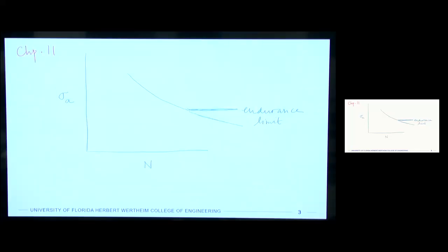And when we started the class, one thing we said was, if you don't have this SN curve, but you need it, but you have material properties, like you have the ultimate tensile strength, and you have the endurance limit, we'll call it sigma E, then you can assemble the SN curve yourself. And what you did is you came up here and you said that whatever point we're starting at was some coefficient times the ultimate strength, like 0.8 or 0.9, and so we could do that. And so that's how we've left this curve.